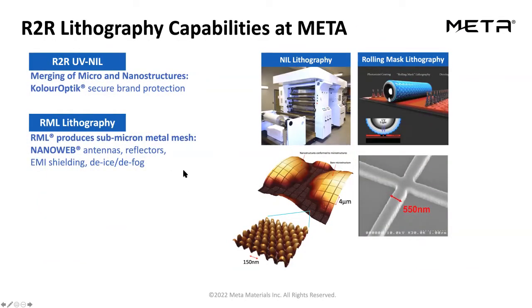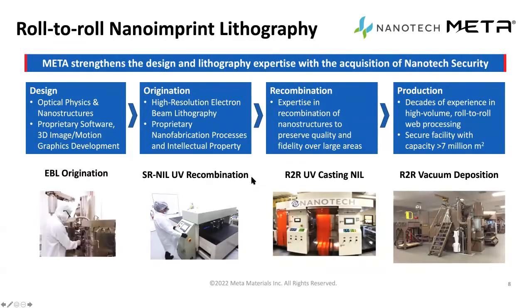And then the mask is fed into 1.2 meter... sorry, somehow it got back. So once the master is fabricated, it's fed into a 1.2 meter wide web UV cast NIL, which can print really fast, up to 150 meters per minute of these nanostructured coatings. And then in the last step, we do a roll-to-roll deposition to basically coat these structures.